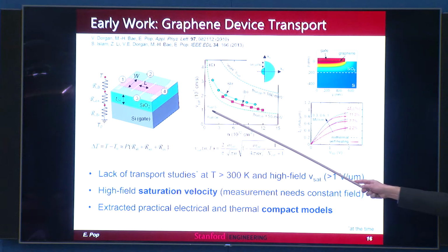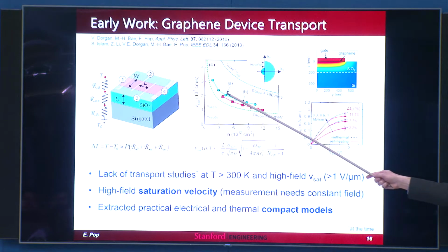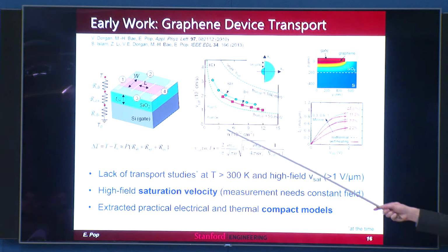In silicon, it's about 10 to the power 7 centimeters per second. In germanium, it's a little bit less than that. It varies a little bit on doping and temperature, obviously, but in general, they're pretty well known. In graphene, the numbers are higher, maybe a factor of 2 to 3 times higher. But the surprise at the time was that they're actually a function of the carrier density. And that has to do with the funny band structure of graphene.